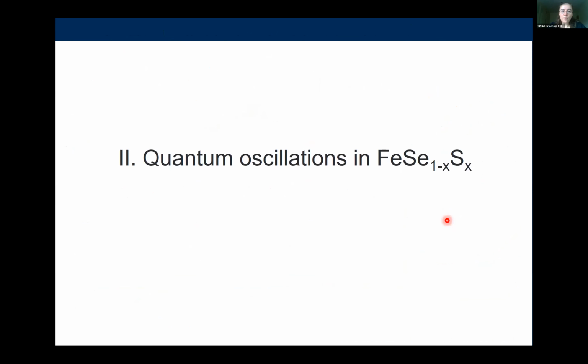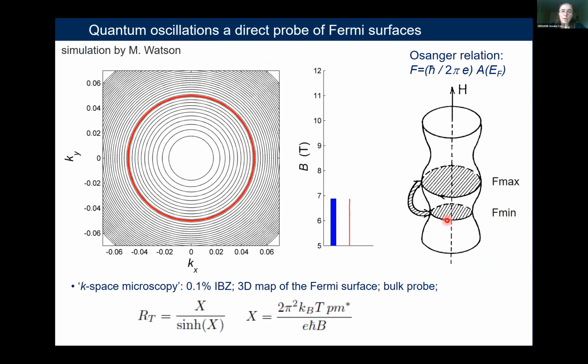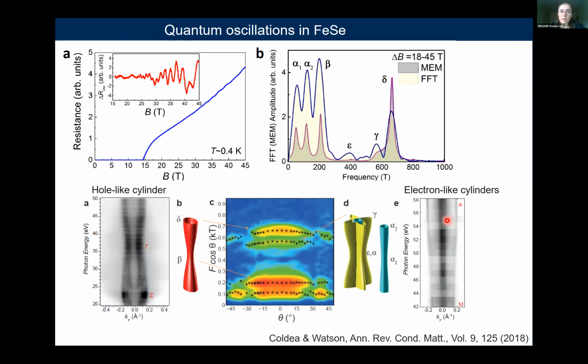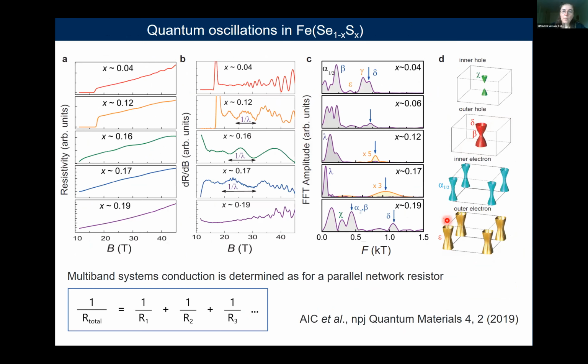I only have a few minutes left, so I will probably go quickly through what we learned from quantum oscillations. Quantum oscillations is obviously a different probe compared with ARPES. Here we measure transport, so we expect the resistance to be dominated by the most mobile carriers, because the system can be thought of as a parallel net of resistances with different contributions from different bands. What we learn in quantum oscillations is that from about 12%, which is the concentration for which the new three-dimensional little carrier appears, we see a very slow frequency developing, and that frequency survives all the way to the nematic transition and then disappears.